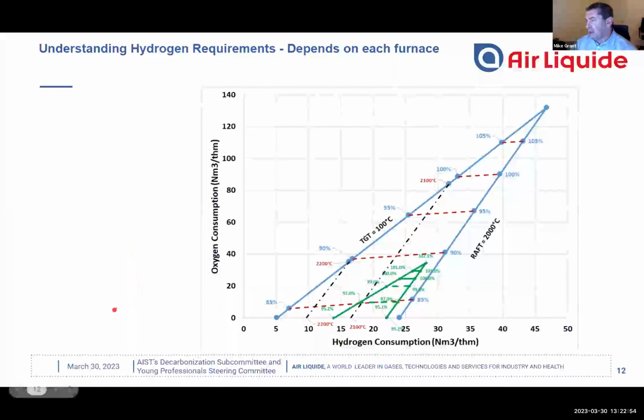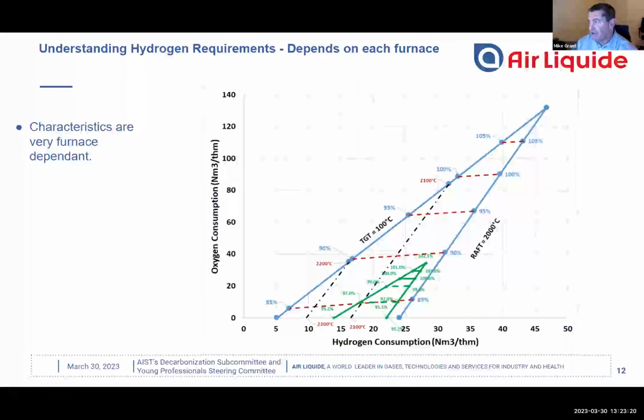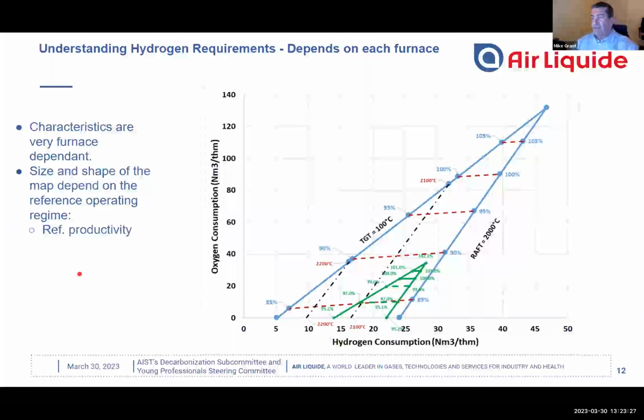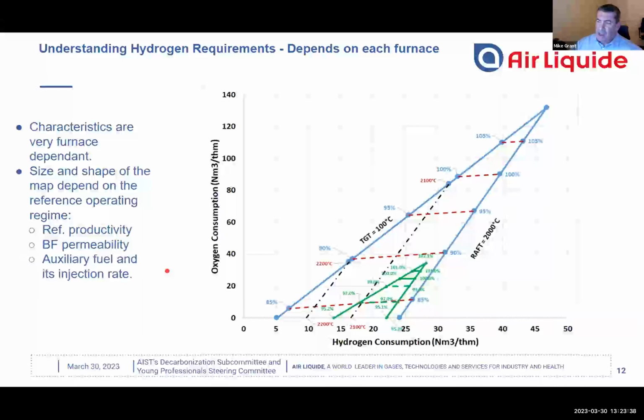This effect, of course, is furnace dependent. So this little green map here was the same as the one I just showed you. And a larger one is for calculations I did for another furnace. And this particular furnace can actually accept up to 47 Nm3 of hydrogen, which is quite unusual, but it's very furnace dependent. And in this case, this particular furnace would be able to get more benefit out of the hydrogen injection. It's dependent on many different things. The reference productivity, of course, is very important. If the furnace was already at close to its maximum, the permeability has an effect. And of course, how much auxiliary fuel rate was being injected prior to the hydrogen being introduced.